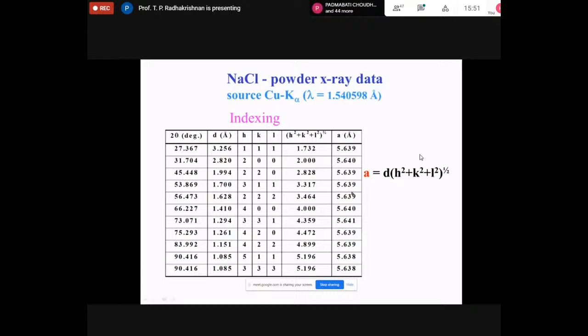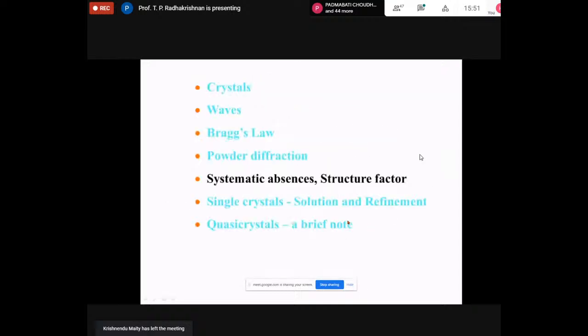So you can basically finish this indexing, and once you do that, you can get a picture of which crystal system the crystal belongs to. In this particular case, sodium chloride nicely fits a cubic system. So immediately I can say, yes, sodium chloride belongs to a cubic system. But from the textbook, we know that it is not only a cubic system, but also a face-centered cubic system. Now, this simple crystal indexing doesn't tell us whether it is a primitive, a face-centered cubic, or a body-centered cubic, unless we look at this important concept called systematic absence.